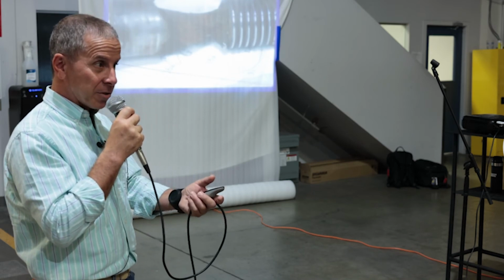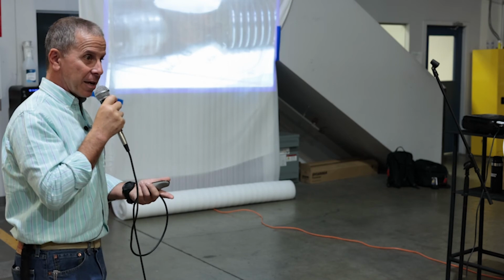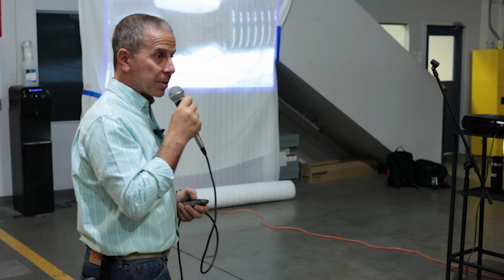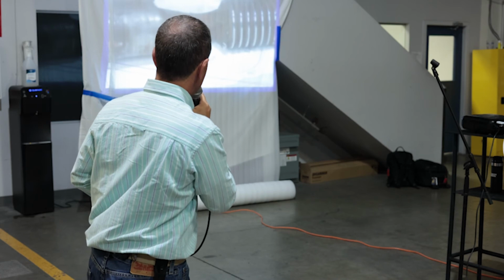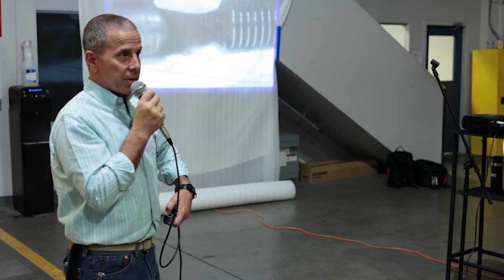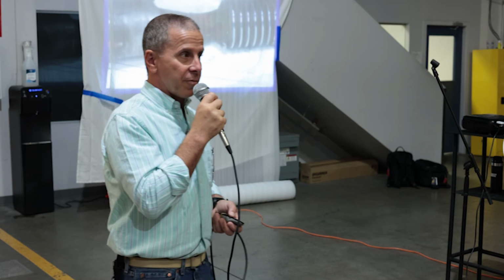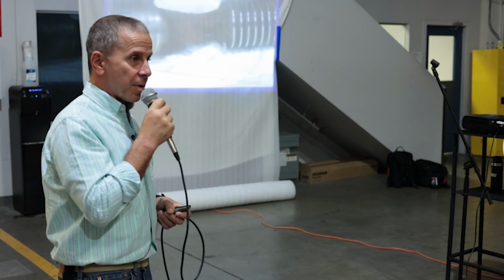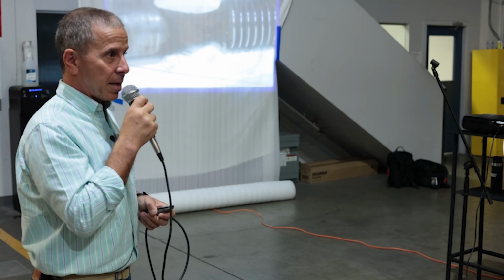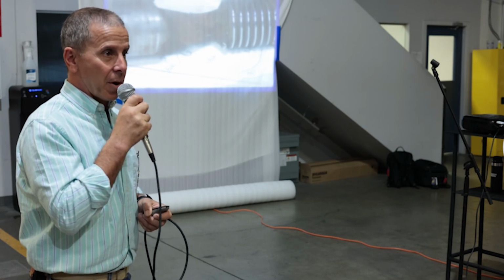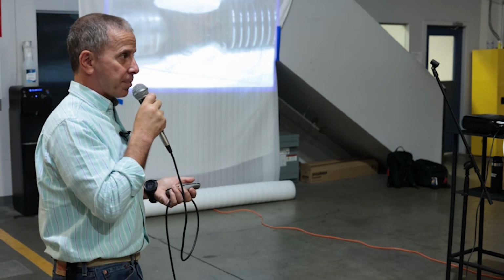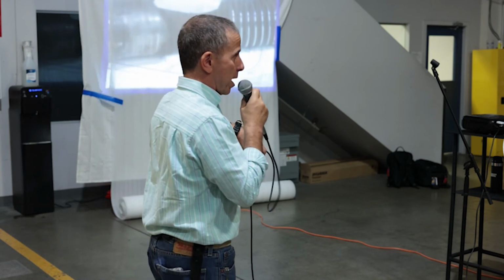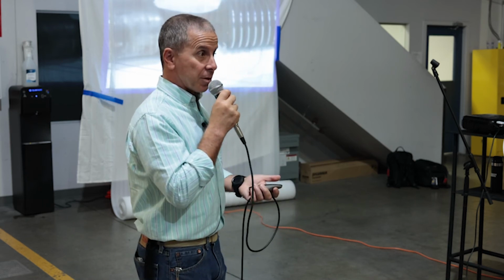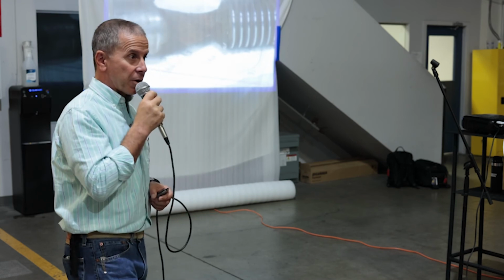A wire has chafed against a fitting and it is now leaking into the hull. That can happen as well. Okay, so crevice corrosion is the most common type of corrosion that attacks stainless steel. Now, for stainless steel to remain corrosion resistant, it needs exposure to one thing primarily, and that's oxygen. It needs air. When it is exposed to air, it develops a very resistant oxide film that keeps it stainless, essentially, that keeps it from corroding.